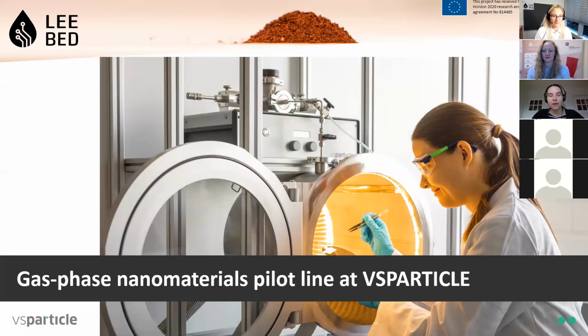That is a good question. We haven't done a lot of studies on flexible substrates. Most customers we had have rigid substrates, mostly chips, and there we do not have a lot of mechanical strain. Indeed, I would expect that the very porous layer would crack readily. This could be improved by annealing. You anneal and you strengthen the layer.